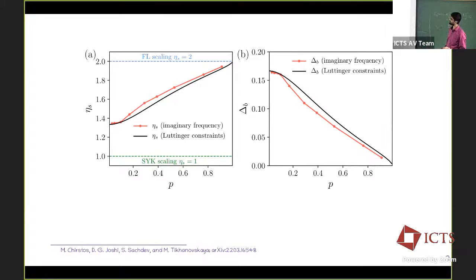And then on the left plot, this is the corresponding exponent for the spin correlator, which is essentially related to delta B. It's 2 minus 2 delta B or something like this. And what you see here is that as a function of doping, as expected, the spin exponent is changing, and it in fact increases as you increase doping. And only in the limit of very large P does it approach a Fermi-liquid-like exponent.